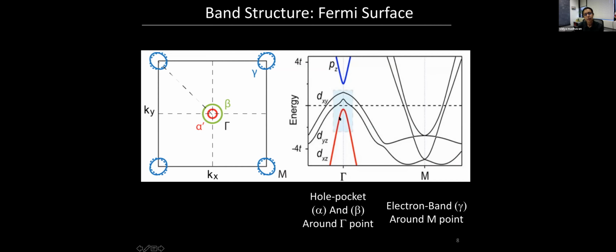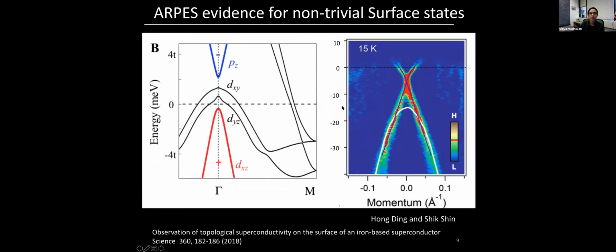But what really is expected to happen is that as you go from any of the end members, FeSe or FeTe, to the middle, this P band and D band come closer. And once they meet each other and reopen a gap, that's when you have band inversion. And that happens for some range of compositions in this compound. But because of this band inversion right here at the gamma point, you expect to see topological surface states. And that's what Hong Ding and Shik Shin showed in 2018. They did ARPES, and what they could see is linearly dispersing states in this sort of narrow region right here near the Fermi energy.